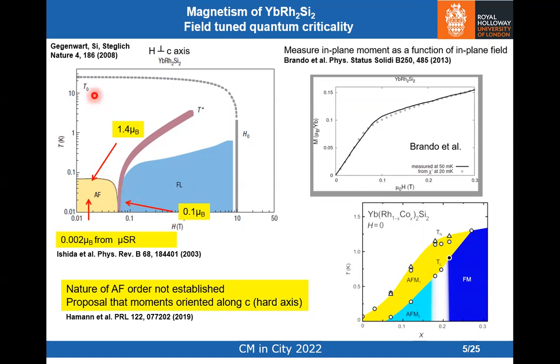If you measure resistivity going down in this direction, it has this linear T dependence and then goes over to a Fermi liquid dependence below the Néel point. So although we know the size of the moment, the nature of this order is not established. We don't know the direction of the moment.